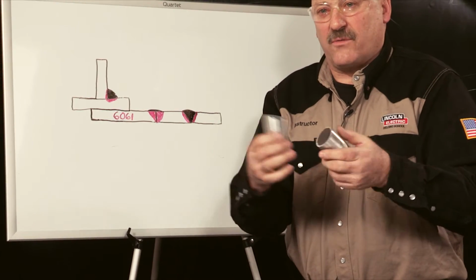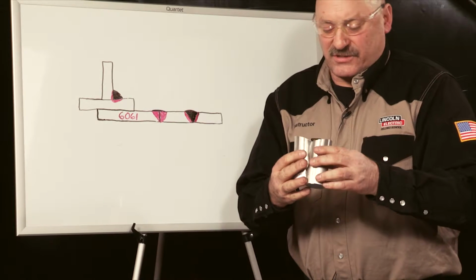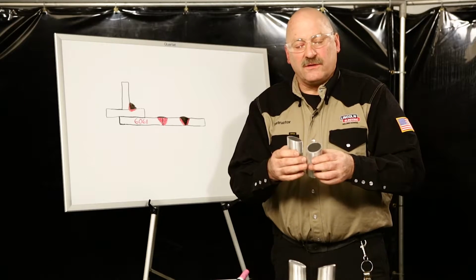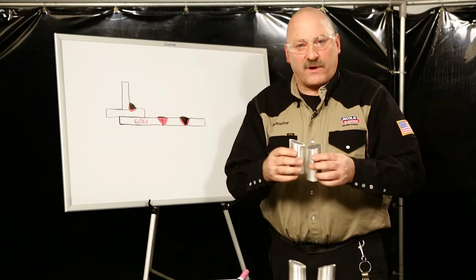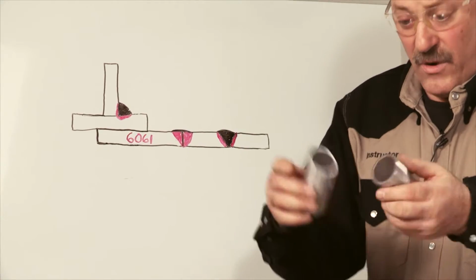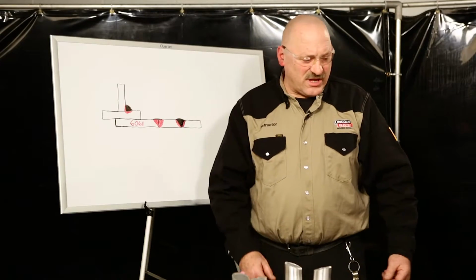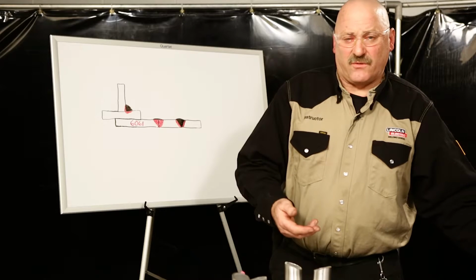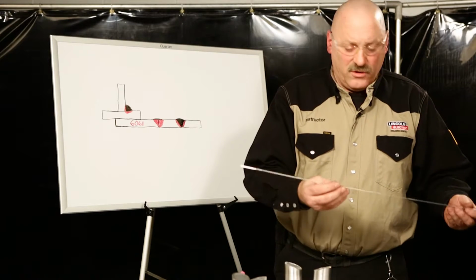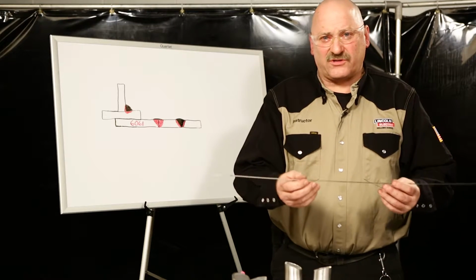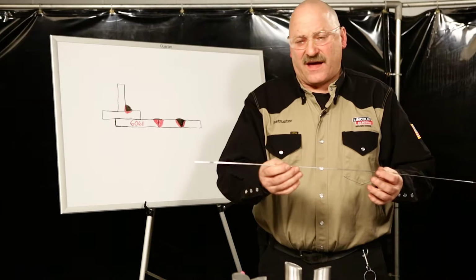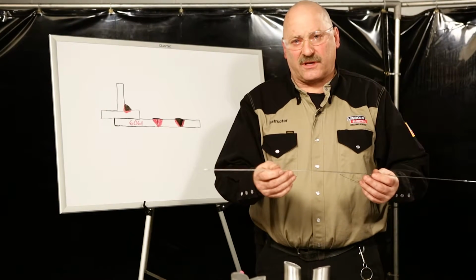This is 6061 T6 material. It's a little over 1/8 of an inch thick. So penetrating down inside, I'm going to get quite a bit of base metal in that weld on this one here. For today's demonstration, we're going to weld this 6061 T6 pipe up with a 4043 filler metal. It's an alloy with approximately 5% silicon. It's an aluminum silicon alloy.